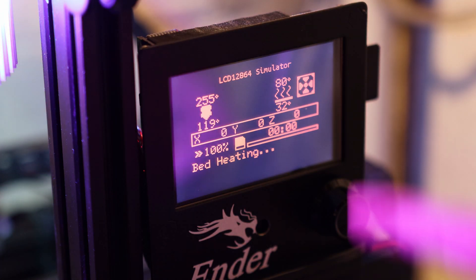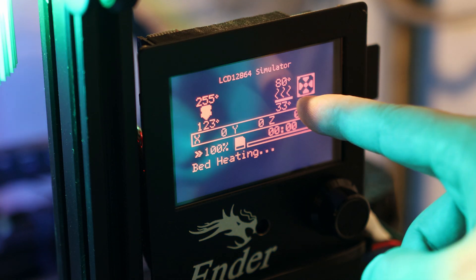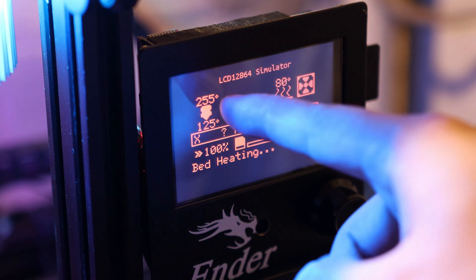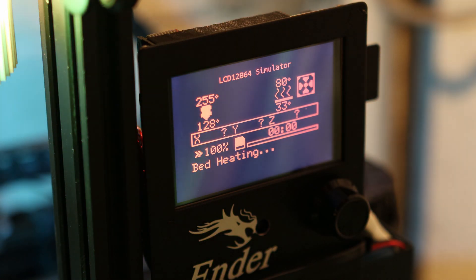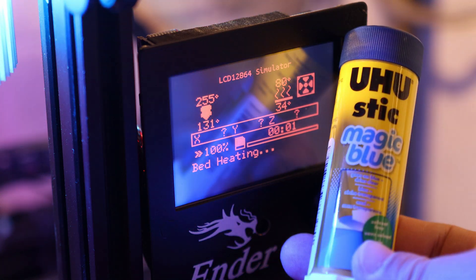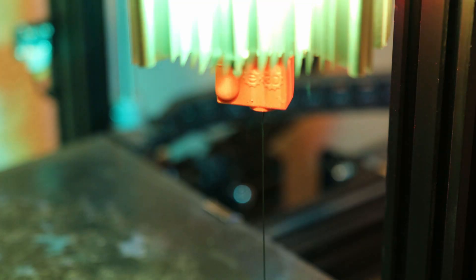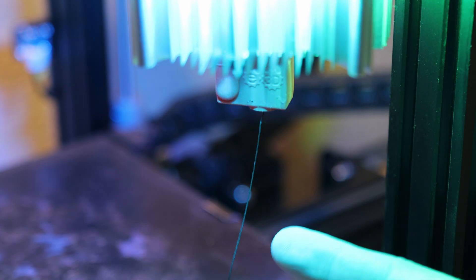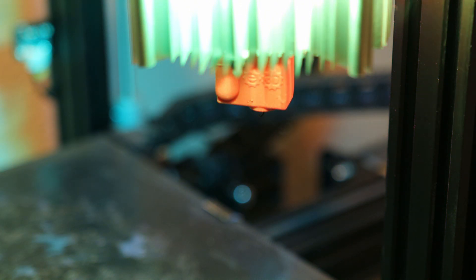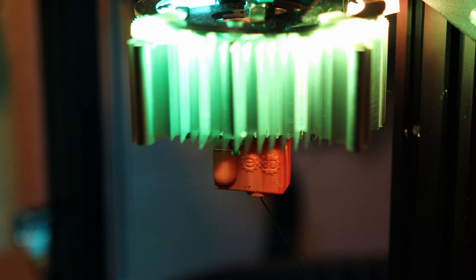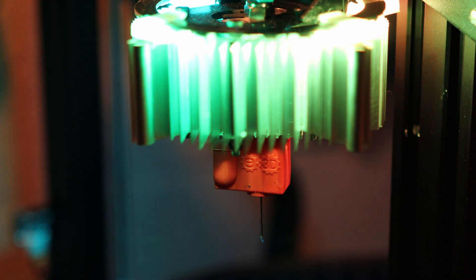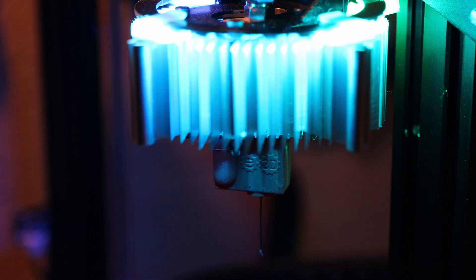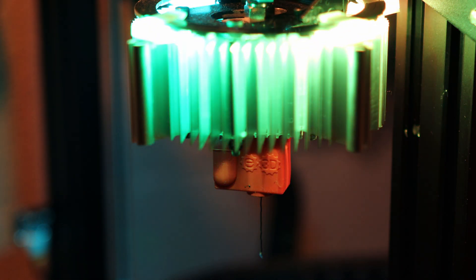I'm going to be running with a bed temperature of 80 degrees Celsius and a nozzle temperature of 255 degrees Celsius. I'm going to apply some of this magic glue stick. SainSmart recommends using a 0.6 millimeter nozzle or above for this filament. It looks like the carbon fiber is letting out little wisps of smoke, so I don't know if that's steam or some kind of other bad stuff, but that's one of the reasons why I'm doing this out in my garage.